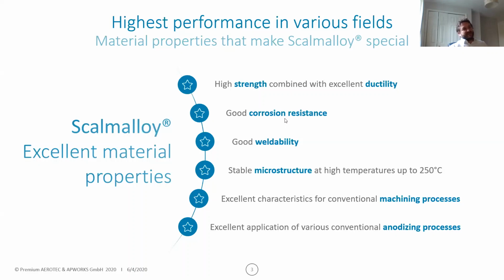Scalmalloy also benefits as it has a magnesium basis to it with good corrosion resistance. So it behaves like a 5000 series aluminium alloy, which is to say it has quite good corrosion resistance for an aluminium alloy. And coupled with the strength, it's quite unique in that respect. It has good weldability. Obviously, that's important for additive.